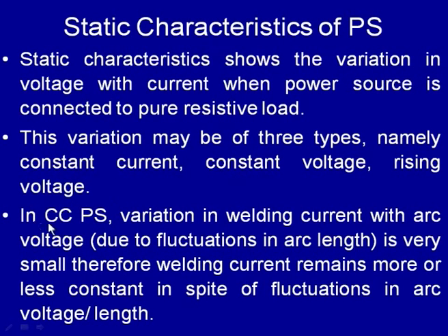So, the main benefit of this constant current type of power source is that the variation in welding current is very small even when there is a variation in arc voltage or arc length, so that the heat is generated uniformly at the same rate, the melting rate of the electrode remains the same, and the penetration remains unchanged. This helps in developing a uniform weld bead and a weld joint having better characteristics. So, under conditions when there is a fluctuation in arc length due to manual control or fluctuation in arc voltage from the power supply, this type of power source helps in obtaining largely constant current for welding, so that a good and sound weld joint can be made.